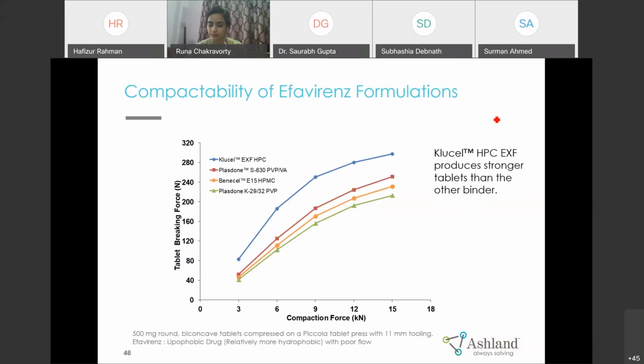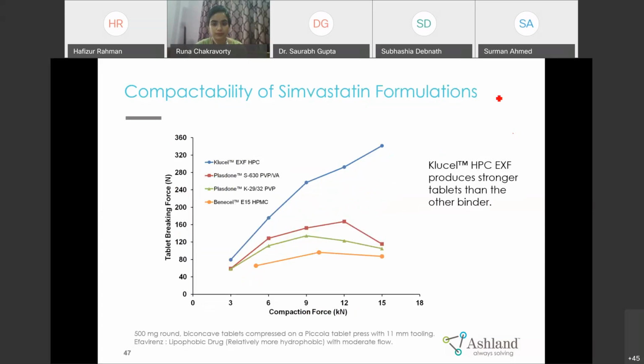Then coming to efavirenz, which is again less soluble than albendazole, we found that tablets are stronger with Klucel, then with copovidone, and then with povidone. Then coming to simvastatin, which is a highly hydrophobic, low soluble API, there we got a significant difference with Klucel and the other binders. So it clearly tells us that if the API is low soluble, then we should use Klucel as a binder, because it has both hydrophilicity and hydrophobicity, and it has better toughness. So it gives the stronger tablet when compared with other binders.